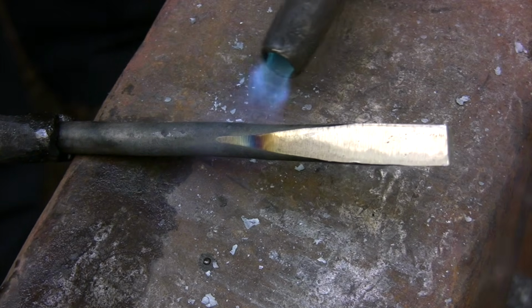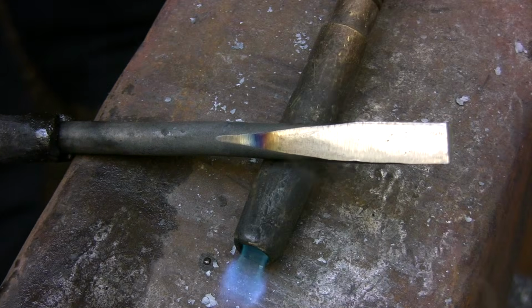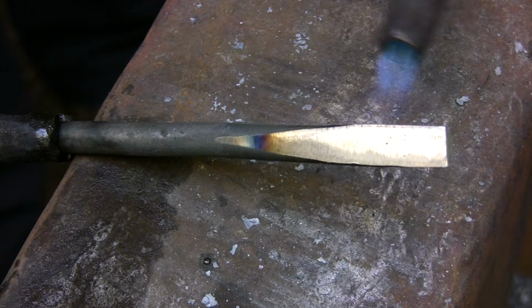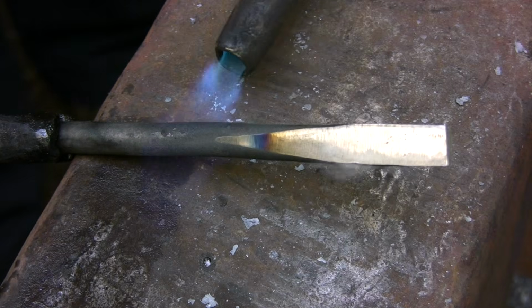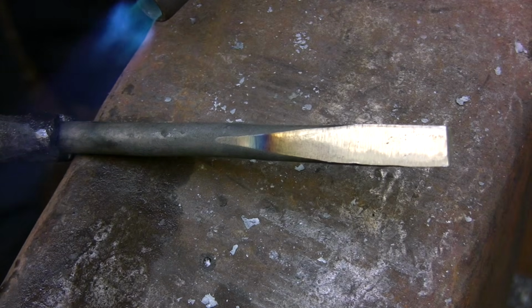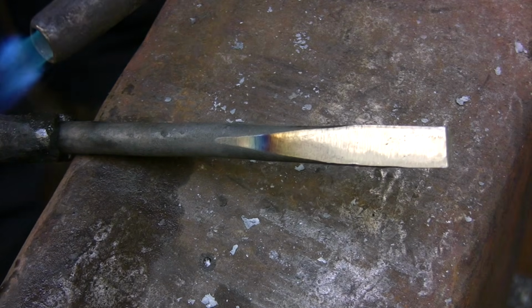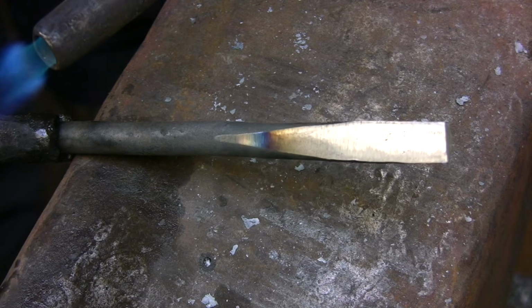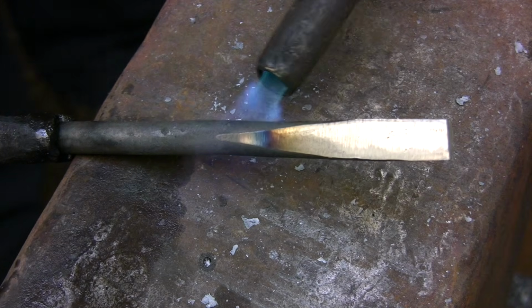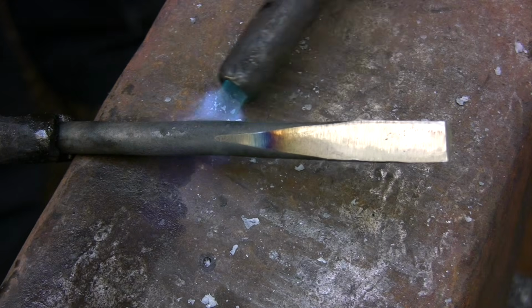The key is to make sure that you take your time getting the first colors to appear. You want the whole tool to be hot. You don't want the colors to just run along the surface because the surface is at the right temper color. That'll create a tool with a soft exterior, but the center of the tool will still be brittle. That'll cause it to fail.